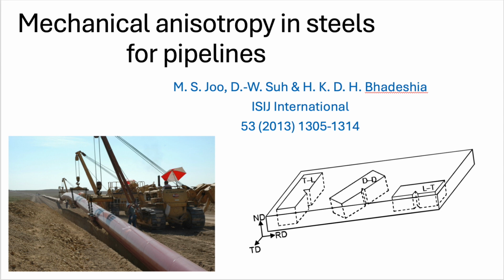So they form little balls instead of pancakes. Pretty much. They create more spheroidal inclusions that don't elongate easily during rolling. That prevents those weak planes from forming. It's called inclusion shape control. Okay, that handles the foreign invaders. Let's move to culprit number 2. This isn't about impurities, but the steel's own structure, right?